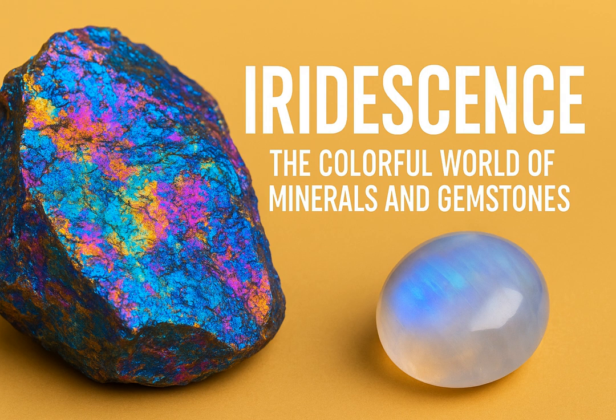So tiny layers of one feldspar inside another? Essentially, yes. And because there's a significant difference in the refractive index, how much light bends between these orthoclase components and the surrounding matrix, the crystal becomes optically heterogeneous. Meaning light behaves differently in different tiny parts. Exactly. Light interacts differently as it travels through different parts of the structure, causing it to interfere and reflect in